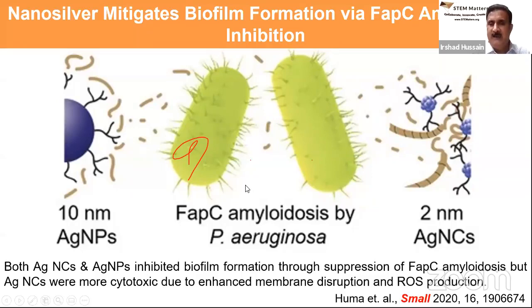basically strengthens the biofilm. And we noticed that both of these nanoparticles are very effective to inhibit FAPC fibrillation. And finally, these 2 nanometer clusters were found to be more effective cytotoxic, mainly because of their higher surface area, for example, and they were able to puncture, to rupture the cell membrane of bacteria, and they released higher concentration of reactive oxygen species compared to larger silver nanoparticles. So these 2 nanometer silver nanoclusters were really more effective to kill bacteria, even while they were hiding in the biofilm. But both these particles, whether they are 2 nanometer or 10 nanometer, were able to inhibit protein fibrillation